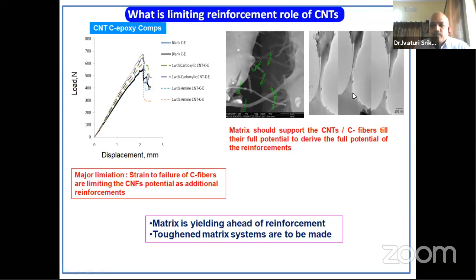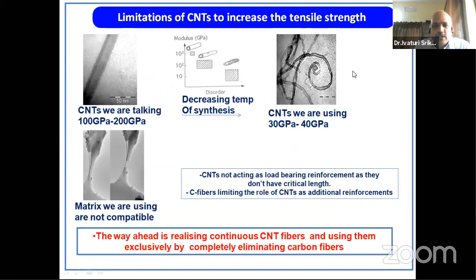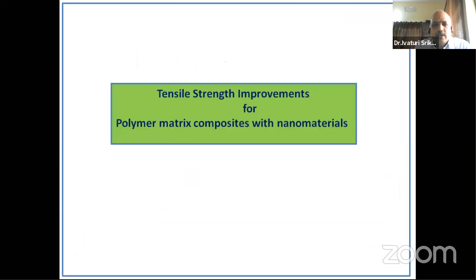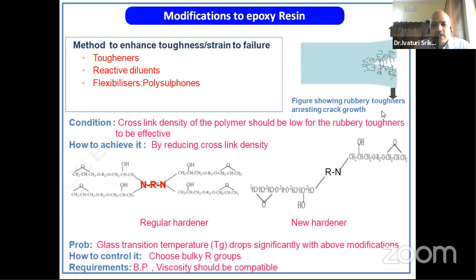As I told, the process we have adopted is the carbon fiber reinforced matrix process, and the resin systems that we have used are those suitable for carbon fibers. Carbon fibers have an elongation of 2 to 3%. Not only we, across all the labs, people were trying the same resin systems and the same processes that are used for carbon fibers. So we realized that this will not work, and we started changing the resin systems.